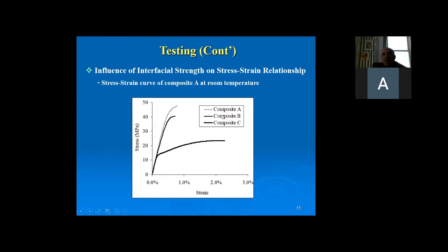Now, and then composite B, we don't use the adhesion promoting special glue between the filler and matrix, but there is still cohesion between the matrix and the filler. The ultimate stress goes to 40 megapascal, but it still fails at almost the same strain level. It is very brittle material, so it's still the filler particles carrying the load.